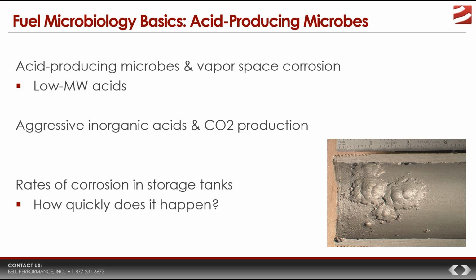There are other bacterial species which produce aggressive inorganic acids like sulfuric acid. And, like we said earlier, they contribute to localized high concentrations of carbon dioxide, which dissolves in water and produces corrosive carbonic acid. Now, having mentioned all of this, one other thing to keep in mind: it is not uncommon to have actual microbial activity in your tank, and yet at the same time, your fuel passes the NACE standard. So that's just one thing to keep in mind, because some people will say, well, my fuel passes the NACE standard, therefore I don't have a microbial problem or microbial presence. And one definitely does not follow from the other.